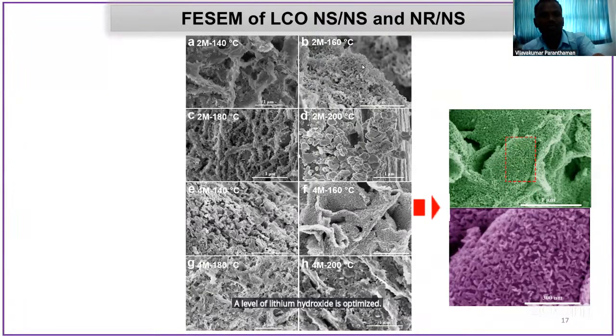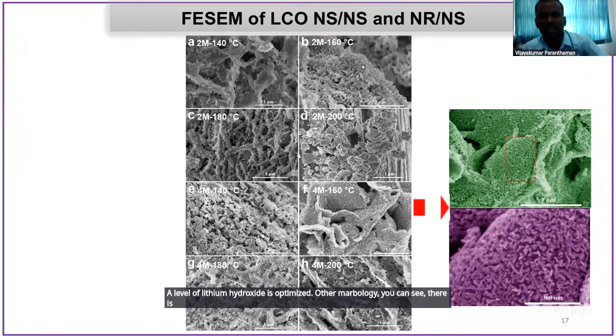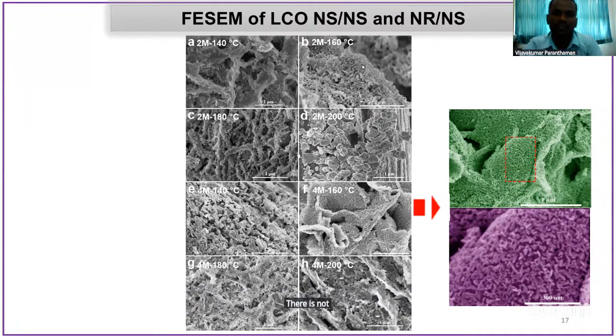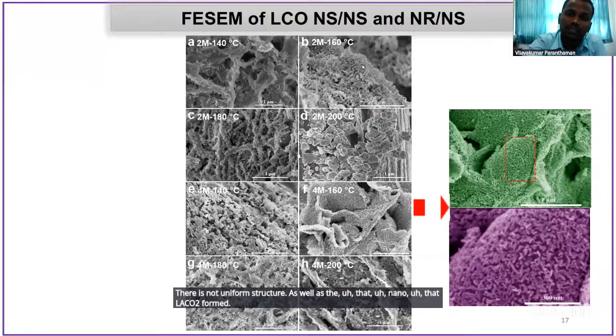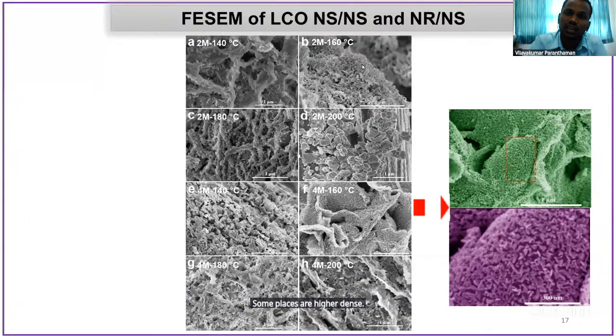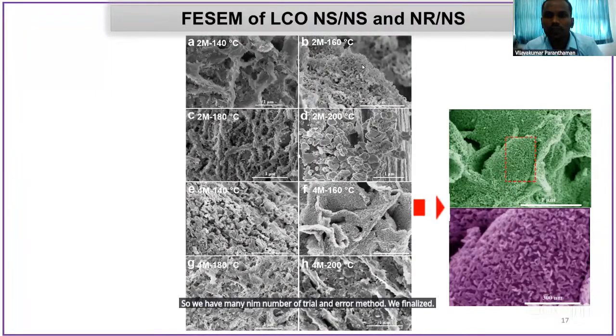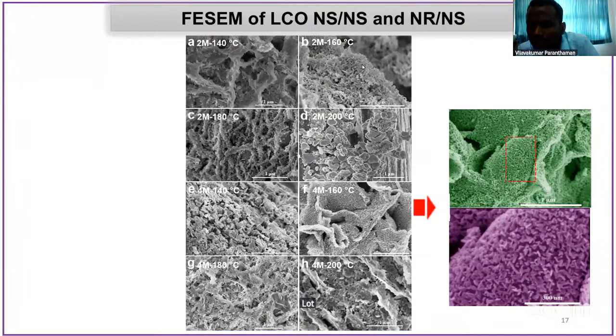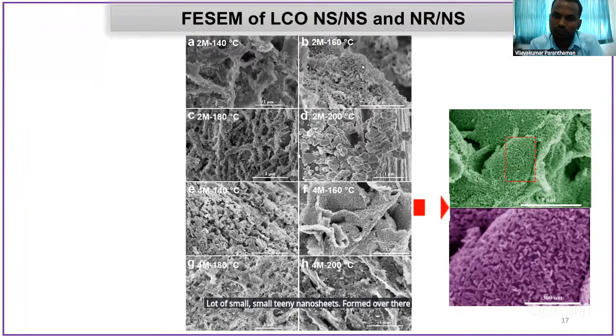Other morphology, you can see there is some agglomeration, there is no uniform structure, as well as the nano LiCoO2 formed. Some places are more dense, some places show the substrate, the carbon cloth substrate. So we did a number of trial and error attempts. We finalized 160 degrees Celsius. Then the expanded image shows lots of small, teeny nanosheets formed over the nanosheets.